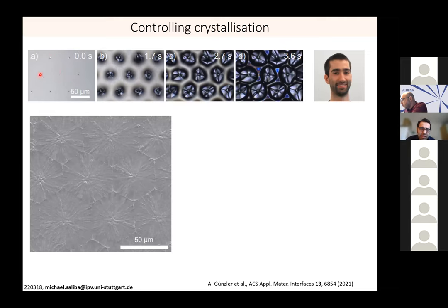And here this substrate is decorated with gold nano dots, let's say. And those have a chemical reaction, the gold surface, with the perovskite precursor. You see it here. And so it means that the crystallization of this liquid film is being seeded. The precursor adheres to these films, and then it starts reacting. And this is used systematically to create the grains of these perovskites. And all of a sudden, although it's a solution processed material, the grains grow relatively systematically and have this hexagonal shape, which is something that we've pre-patterned. So this is a way to induce the manipulation.